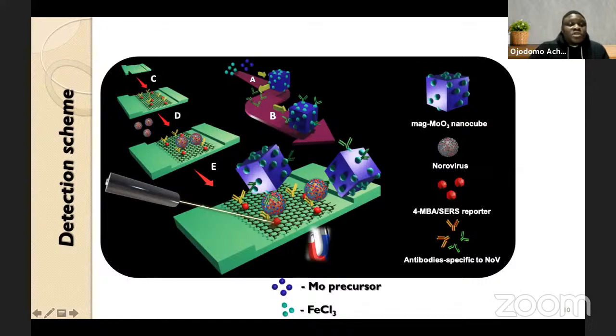So rather than use the bare glass substrate, which is the conventional way of doing your SERS measurement, we decided to functionalize the glass substrate by drop casting and drying single layer graphene on the substrate. Now we equally conjugated an antibody that is also specific towards the target virus on the surface of the graphene functionalized substrate. So now this acts as our capture substrate, whereby from the beginning, before the whole process, we capture the virus before we add the SERS nanotags.